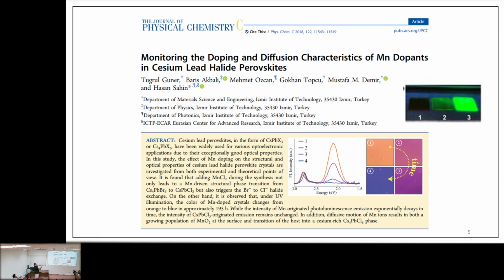It seems that when I tried to dope it with manganese atoms, I was using manganese dichloride salt. So since I was using manganese dichloride, those chlorine atoms, first of all, they substituted with bromine atoms. So it seems that I got cesium lead chloride. Instead of bromine, I got cesium lead chloride. And cesium lead chloride emits blue light, as here. But in the beginning, I had orange color instead of blue.